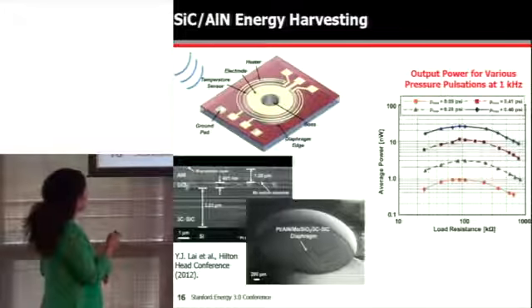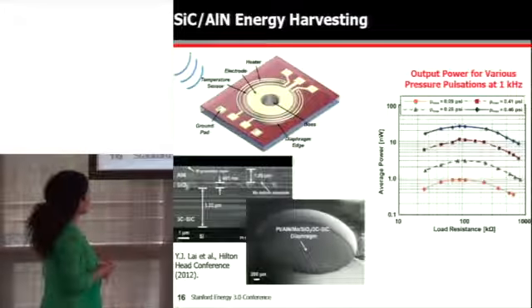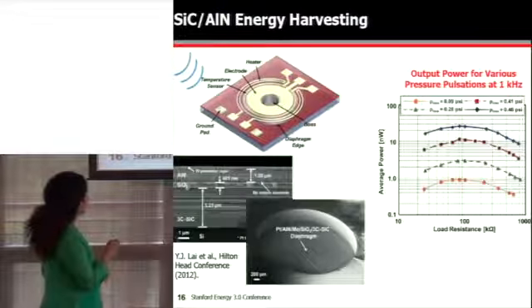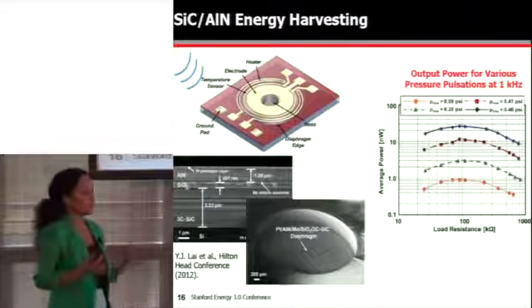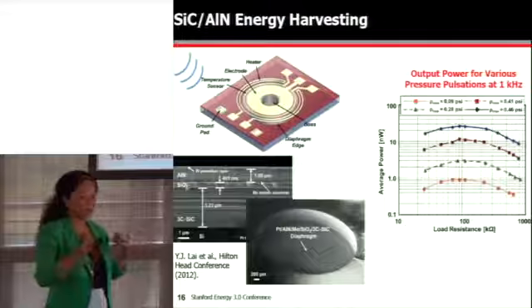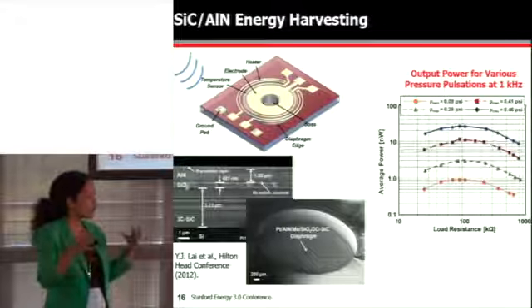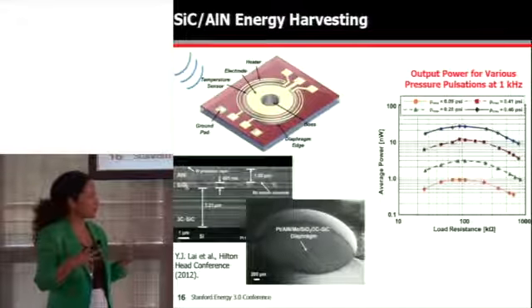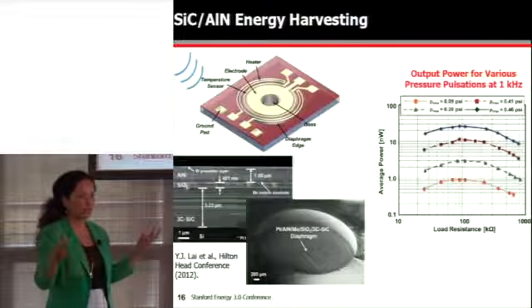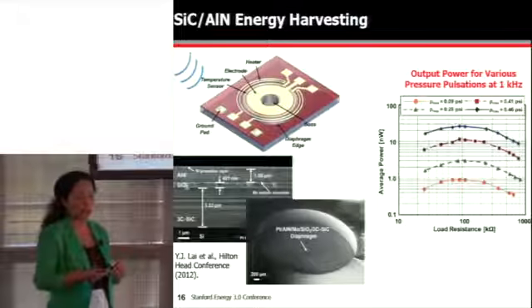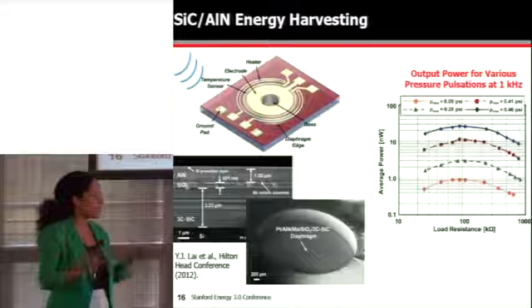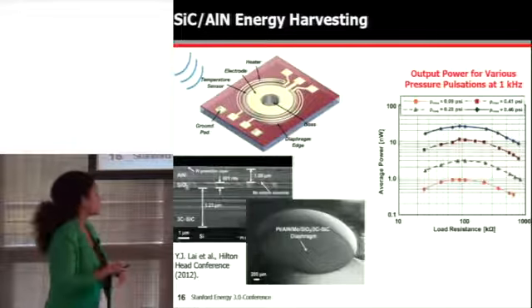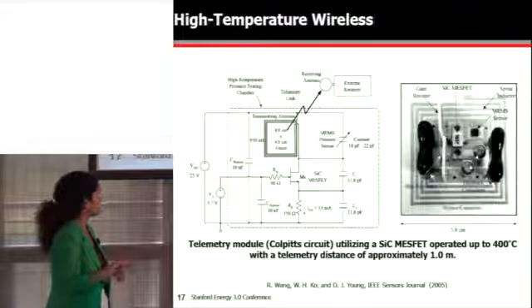This is a diaphragm here that's sensitive to pressure pulsation. It's made of silicon carbide and also aluminum nitride, which is a piezoelectric material. High temperature piezoelectric material, so as you stretch it and it displaces due to pressure pulsation, you could actually generate a voltage. And couple this to a supercapacitor, for example, and power up your sensors and electronics.